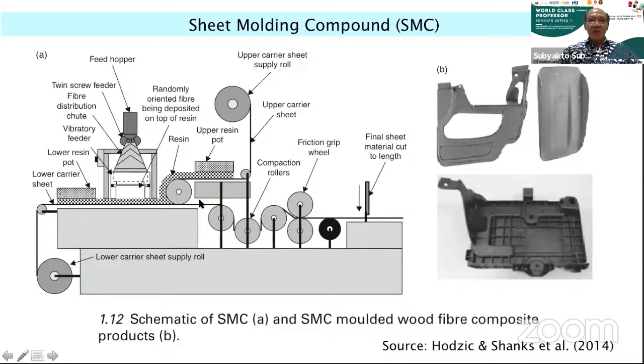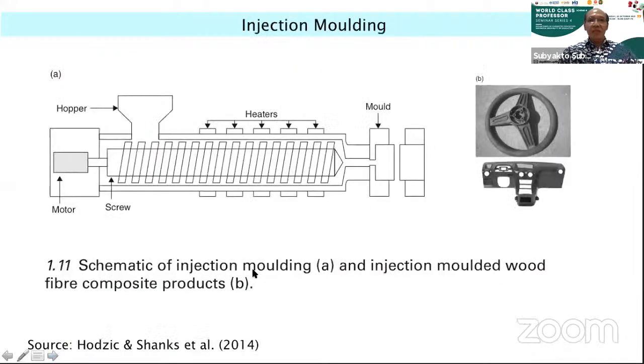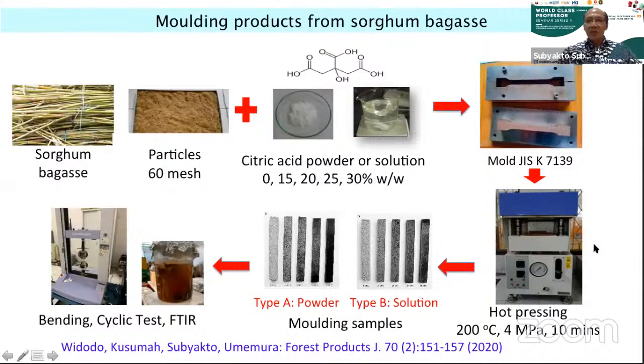And if we talk about molding, we can have a sheet molding compound like this one. So we just put the sheet here and then mold, and we can get this shape. Also, we can use injection molding. So we can get this kind of shape using injection molding. In our work, we use a simple hot press molding, something like this one. So we use sorghum bagasse, make particles, and then we mix with citric acid, and we have two types, powder and solution. And using this mold, we make a specimen with the hot press. And then we test the water resistance and also the bending test.